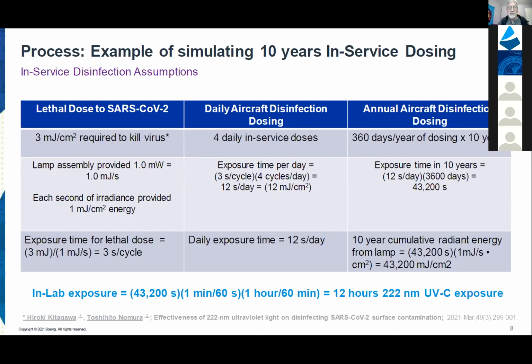That's the estimate we have of the amount of radiant energy falling on a surface that would simulate roughly 10 years of in-service disinfection. And if you then say, okay, well, our lamp is in the hood. If we turn the lamp on after 1 hour, we've got 3,600 millijoules per square centimeter, right? Assuming 1 milliwatt per square centimeter, assuming 3,600 seconds in an hour, that's 3,600 millijoules per square centimeter. So we now have a way of testing in the lab, in the hood, where it's safe, what the exposure would be to estimate years and years of in-service disinfection.